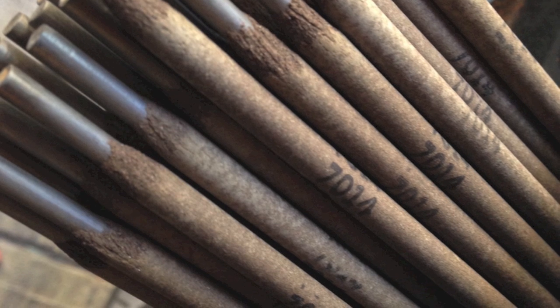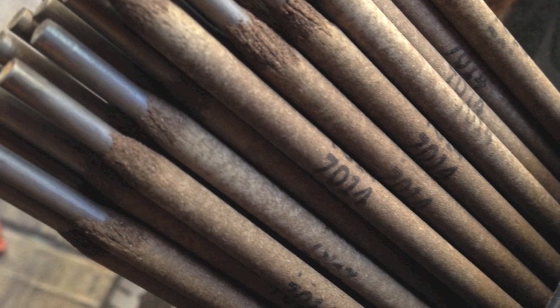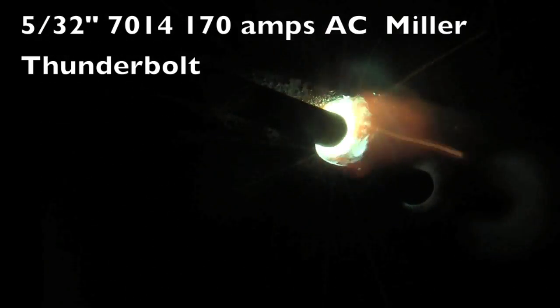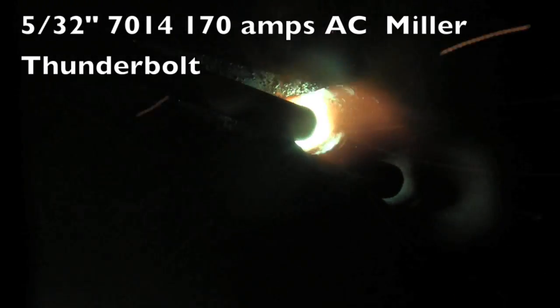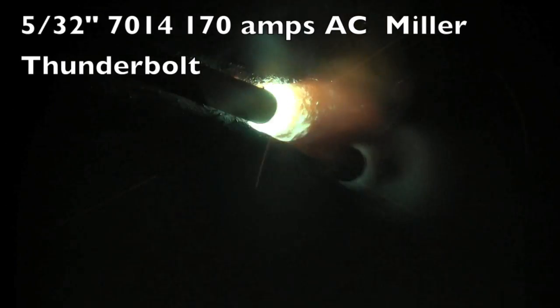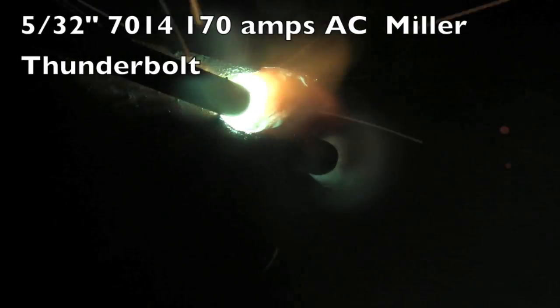So I'm going to switch over to 7014 5/32 diameter, and even going to turn the machine down to 170 amps with a bigger rod. And now look what we got. I got a really hot puddle even with a bigger rod, but it's a lot clearer, a lot easier to see the puddle and distinguish it from the flux.